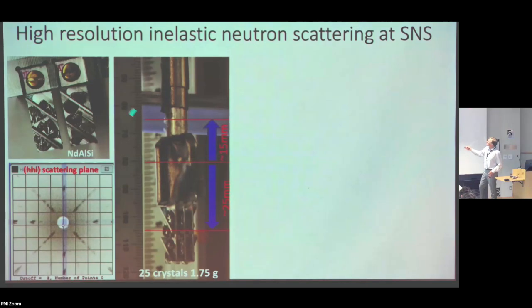But then above that, we had a little region where we thought we would reproduce all of the extraneous material that we have because of mounting the crystals, including the glue and all this crazy stuff that we want to actually subtract out. So this was kind of a background sample, and it's very important that we have it in the same cryostat, because this is all dilution-refrigerator instrument stuff, and so it's a very slow process of cooling and mounting, etc. So in this way, we could actually do our experiment with the crystal, and then just lower the entire thing down to get this into the beam, and do that exact same measurement, then do a subtraction, and that was key to making it work. Without it, it just wouldn't work. So these are just little tricks.